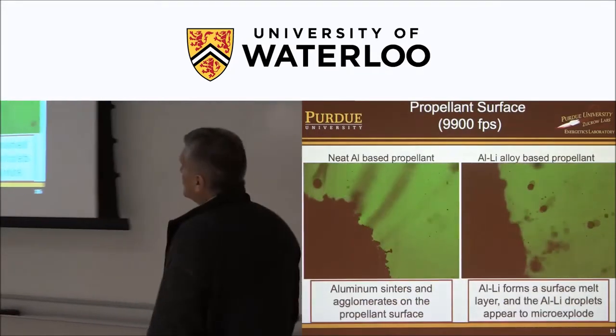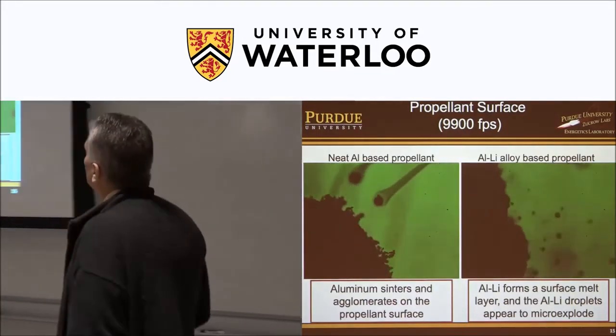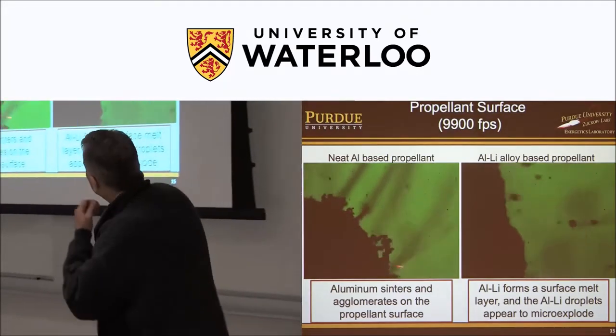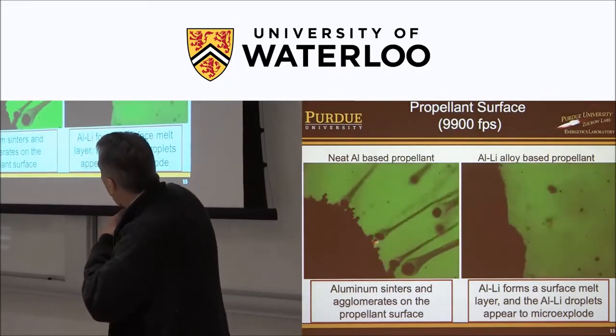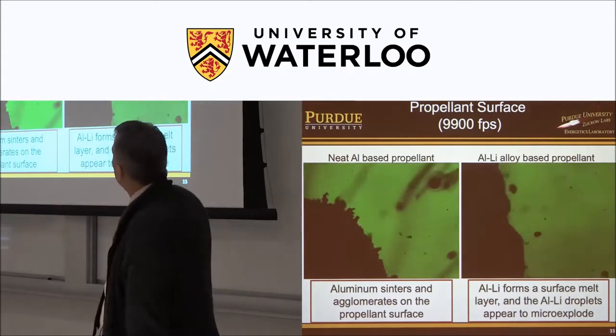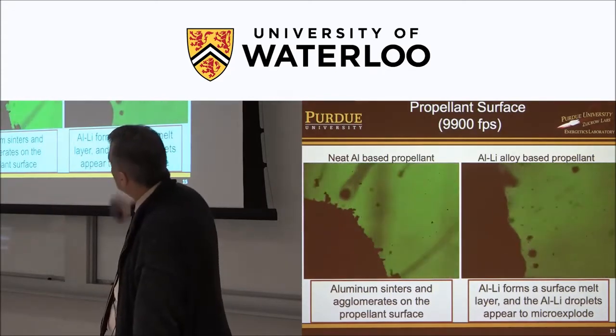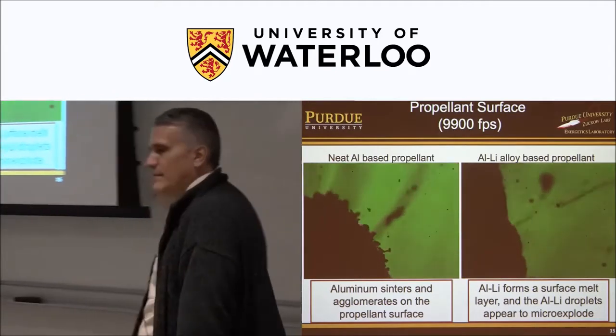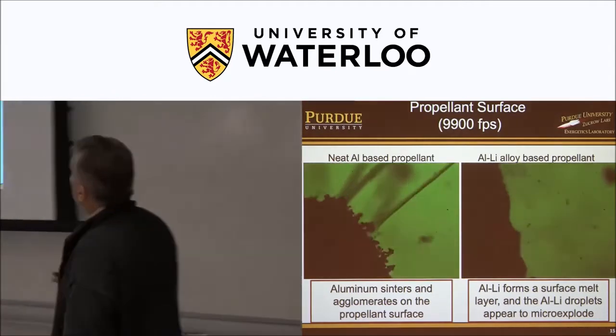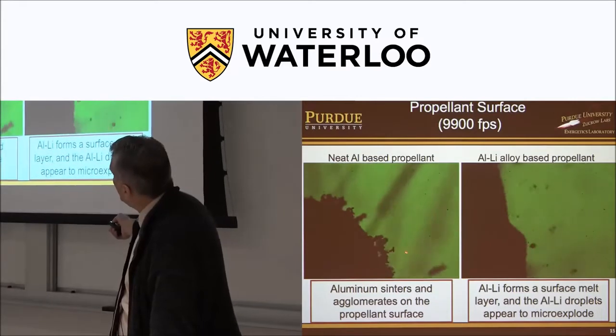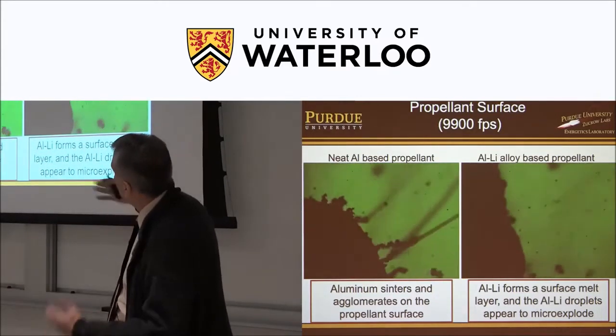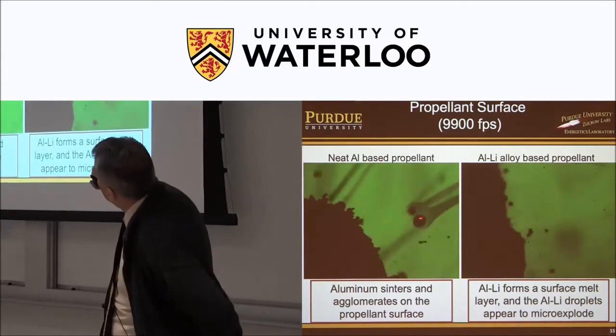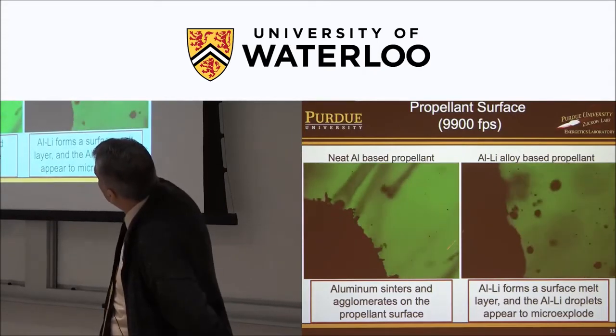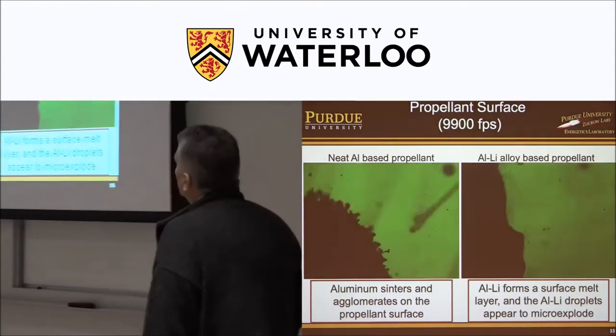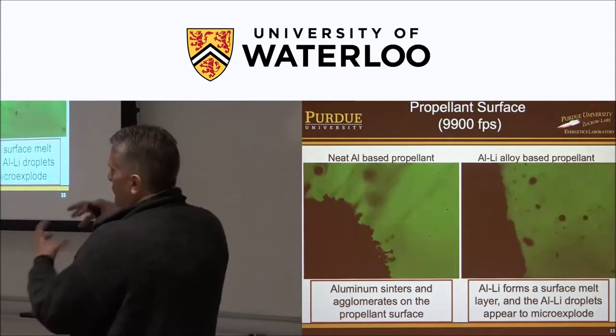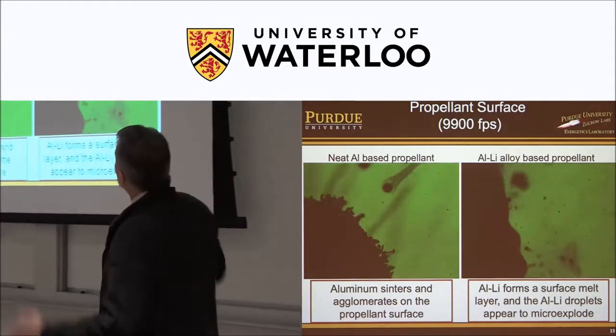Let's look microscopically. We do some backlit, high-speed microscopic imaging. The smallest particles you see here, those are aluminum particles. Those are about 30 microns to give you a scale. The largest, the droplets here are several hundreds of microns, maybe the diameter of your hair. This is all pretty small stuff. But you can see as this surface burns back, and we're not really seeing the flames because of the backlight and so forth. And then you see these aluminum droplets, and the smoke coming off from them is the alumina. And the alumina will agglomerate in big droplets, and that goes clunking out through your nozzle.